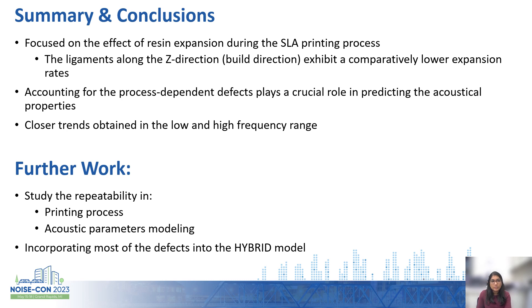In summary, we studied the solid ligament behavior of the thermoset resin for samples 3D printed using stereolithography. We found that as ligament thickness increased, the expansion rate increases quadratically in the XY plane and comparatively lower along the build direction. We observed that the numerical models are under-predicting the sound absorption results, since the unit cell does not fully incorporate multiple defects such as clogging of the pores and non-uniformity of pore size and shape. However, we see promising results when it comes to matching the peak locations, trends, and absorption behavior in the low and high frequency range, especially when using the maximum deviation values.